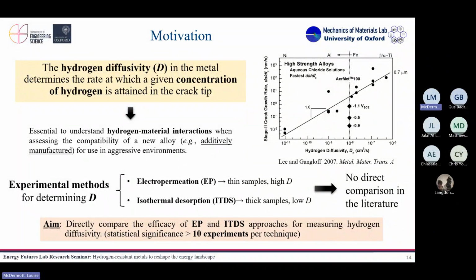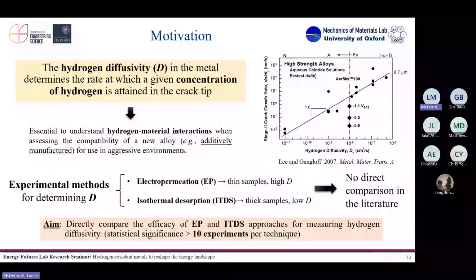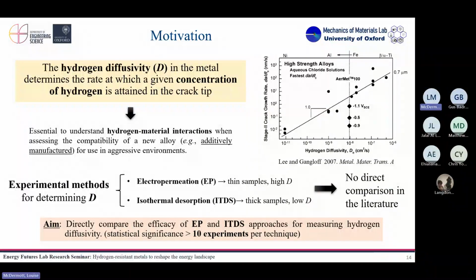And we found that there is not really a direct comparison in the literature to see which technique provides a more accurate or more reliable result. Most of the people rely on electropermeation because it's the most straightforward, but it has its limitations. So the aim of this paper was to compare those techniques from a statistical point of view, performing loads of experiments for each technique and comparing which one could provide, let's say, the more accurate results.